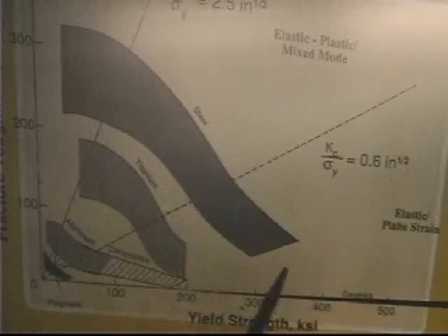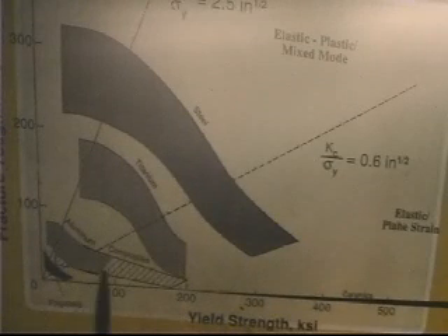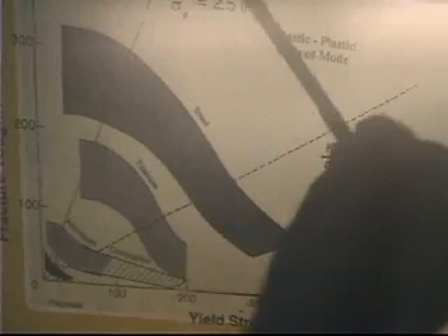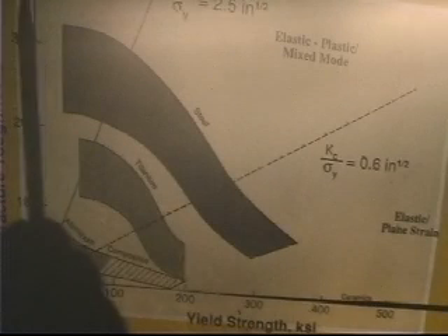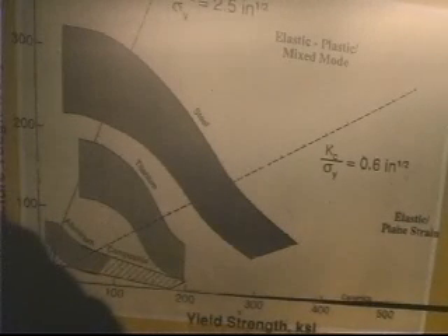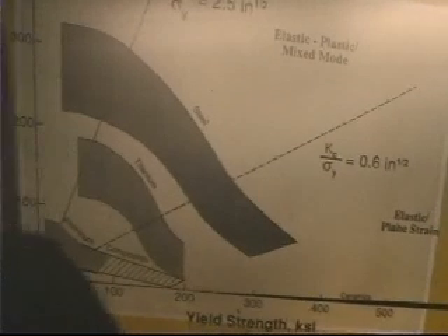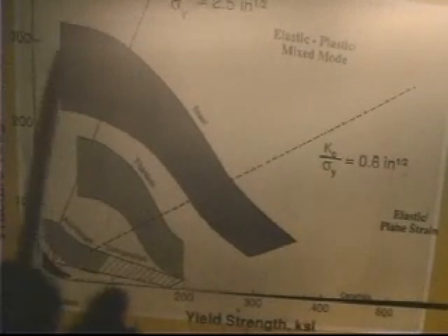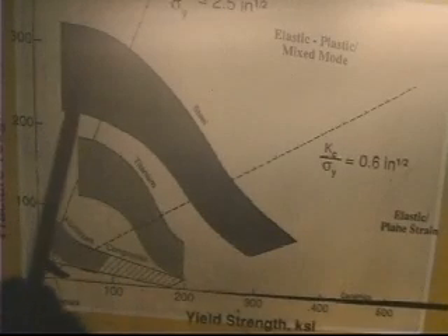This is fracture toughness versus yield strength. Here's steel. Steels tend to follow this band. Titanium alloys are down here, aluminum alloys down here, and composites are down here. You want to be as far out here as possible. Over here you have plastic general yielding. It means you can hit this thing with, you know, a mortar round, a shell, and it's going to deform and bend and absorb a lot of energy. Good armor, high toughness, not necessarily the highest strength, but tremendous toughness, so it will deform before it breaks.